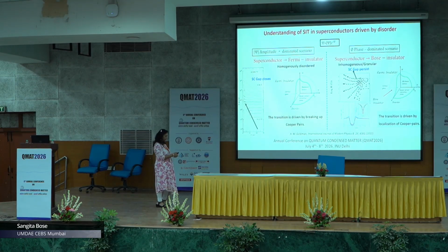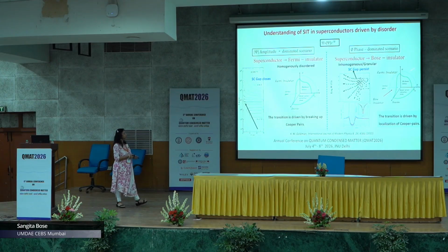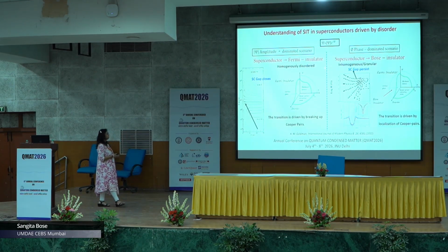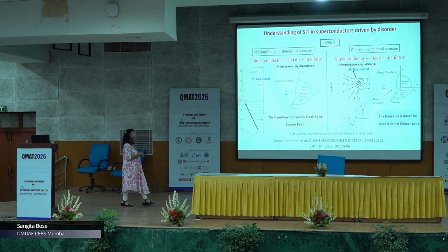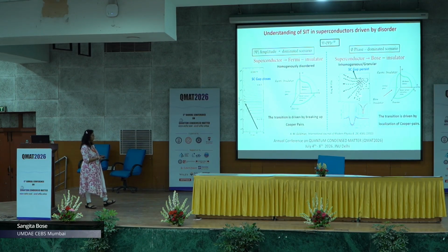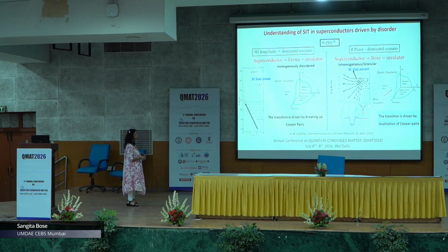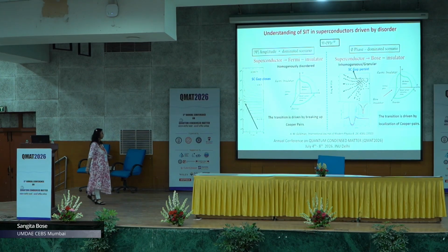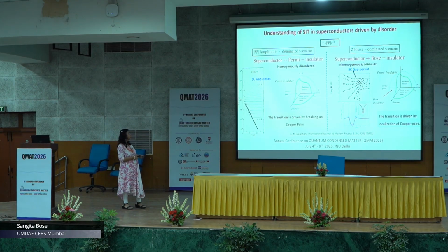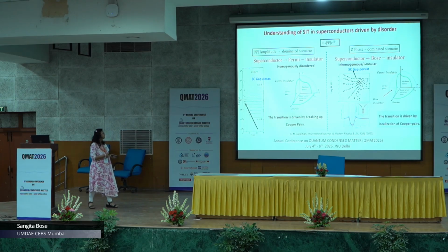However, there is an alternative scenario where you go from a superconductor to a Bose insulator phase, mostly seen in inhomogeneous and granular systems, and this is the phase-dominated scenario. Here the transition is mainly driven by the localization of the Cooper pairs. But if you actually measure the superconducting energy gap in these insulating samples, you would actually see the gap. That means the gap persists in the insulating phase. So this is the understanding of the SIT. Of course, there are controversies. It's still controversial which one actually follows the Fermi insulator scenario and which the Bose insulator scenario.